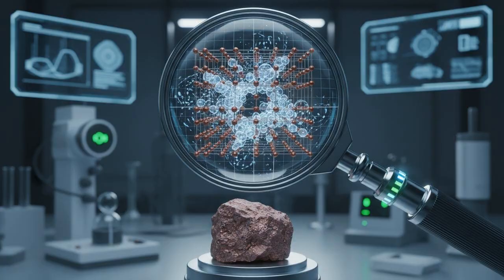Once the theory was in place, the hunt for materials began. The physics community realized that altermagnets should not be rare. They should be hiding in materials we had already discovered, but simply misclassified. The fruit fly of this revolution became manganese telluride. For decades, manganese telluride was a textbook antiferromagnet. But when researchers looked closer at its crystal symmetry, specifically at the non-magnetic tellurium atoms, they realized they sat in a way that broke the symmetry between the manganese sublattices.